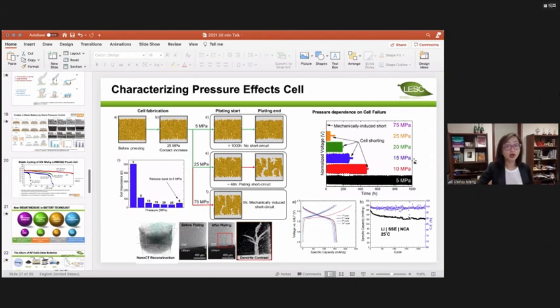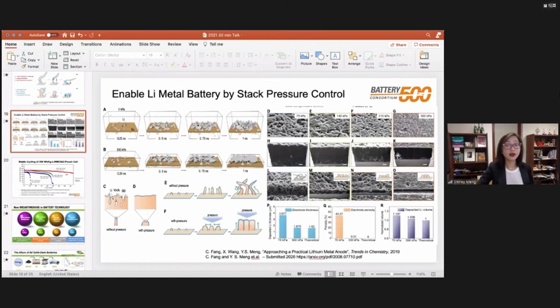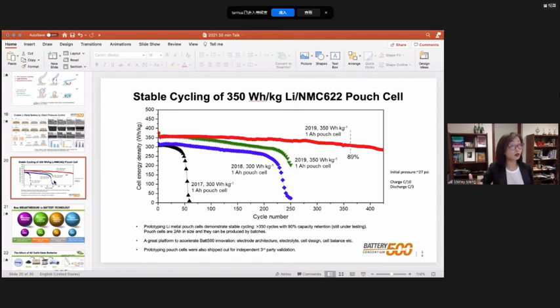But I do want to take this opportunity to address the corrosion problem for lithium metal, even in liquid. If you have very densely packed lithium metal, the corrosion and self-discharge problems are very minimal, because there's almost no contact except for the top surface, which already has the SEI formed. There's almost no direct contact with fresh electrolyte, and we can keep those cells functional with low self-discharge for months and months. These cells have already been demonstrated in large format, with proper evaluation of self-discharge. For solid state, it's still a little bit early, but in the end this question has to be addressed.